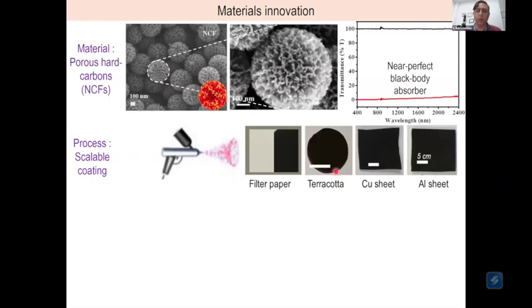For example, you can coat it on the wall of a building like a terracotta or a cement structure. You can coat it on copper sheets, metals like copper and aluminum. You can even coat it on filter paper. The first observation that we see is that it is extremely black in color. Any substrate on which you coat is extremely black, and that is reinforced by these absorption or transmission spectra, where you see that the coated material doesn't transmit any light over the entire solar spectrum, starting from about 400 nanometers, which is where visible starts, all the way to infrared. It's about 95 to 96% absorption of the photons that happens with these coatings.